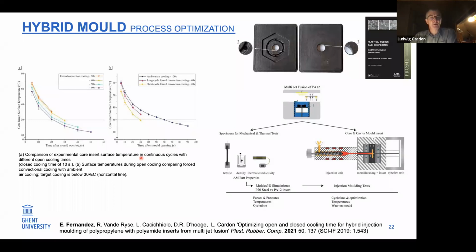So what we analyze in that one too is, let's say, to optimize finally the cooling times, because you want to cool down as fast as possible. I'm not sure, I think I didn't integrate a slide on that one, but what we then design also is the so-called forced cooling. So once the part is cooled down enough to be solid, we open the mold, we eject the part, and then this mold insert, we cool down that one by a forced pressurized cold air stream. So what you see on the left side, instead of standard air, to have a forced cooling, so a faster cooling and a shorter cycle time. So this is an example how we investigate that.